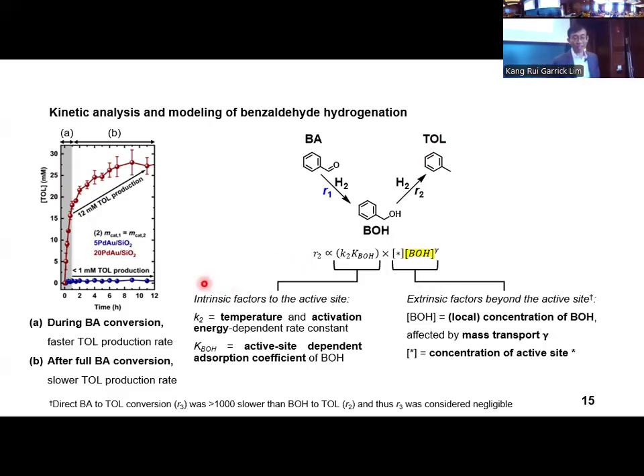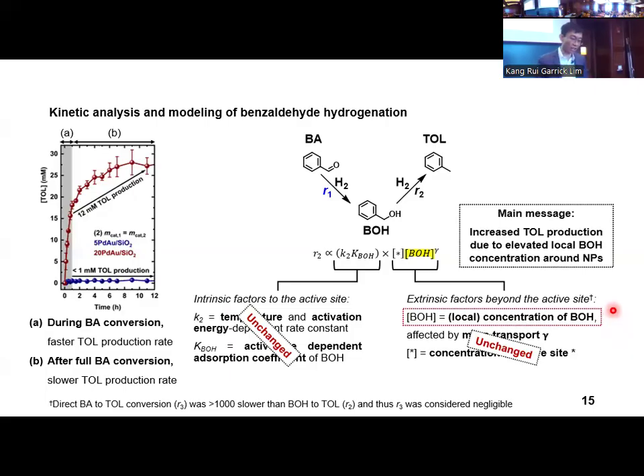To determine any intrinsic changes to our catalysts, we performed ex situ characterization of our used catalysts and found no differences in the nanoparticle size distribution, composition, oxidation states, kinetic rate orders, and the apparent activation energy. It was thus unlikely to us that the nature of its active site and the adsorption coefficient has changed substantially after the reaction. For the external factors, we tested the catalyst at a constant active site concentration using a fixed metal mass and under constant bulk mass transport characteristics using a fixed catalyst mass. In fact, you saw in the previous slide that we tested both these conditions independently and simultaneously, and the selectivity differences still persisted. Ruling out these reasons led us to deduce that differences in the local benzyl alcohol concentration amongst the catalysts caused by the different interparticle distances as the most plausible explanation for the selectivity differences.